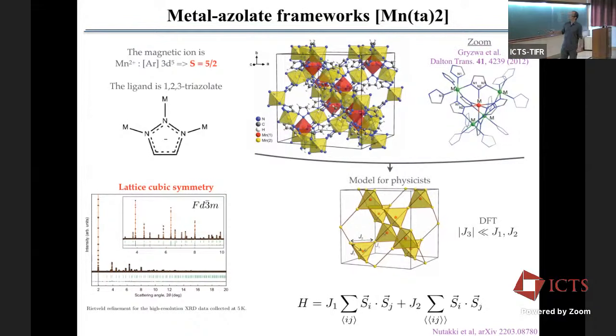Now we have done DFT calculations of this structure, and we have found that J1 and J2 are actually comparable in strength, because in one case, between these two, we have 2 nitrogen ions in between, and between these two, we have 3 nitrogen ions. So actually the path between them is just 1 more nitrogen ion, and that's not a big difference as far as the strength of the coupling is concerned. And so we will see that the ratio of J1 and J2 is actually not so far from 1. But on the other hand, J3 is much smaller.